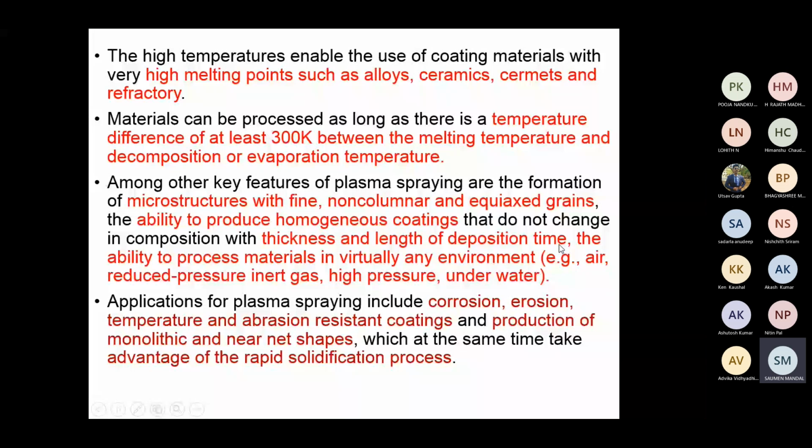In physical vapor deposition, if you change the thickness, the morphology will change. But in this case, it does not happen. Whatever particle comes, it sticks there, so it will not change. If you increase the thickness, the morphology will not change. And if you deposit for a longer time, it will also not change, because we are not doing any substrate heating. Here the film formation pattern, the coating pattern, is different.